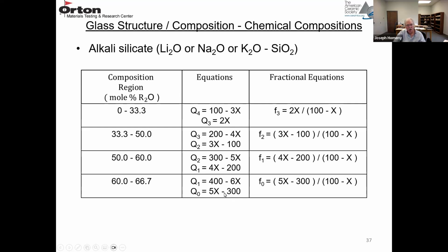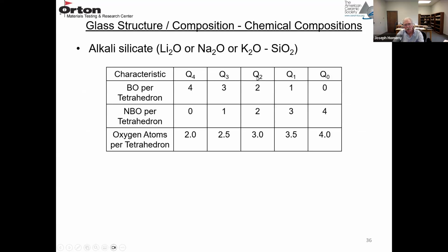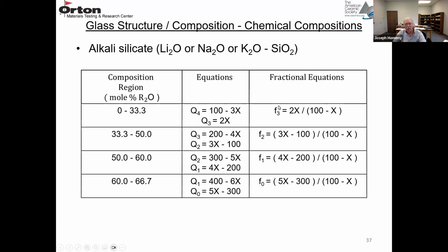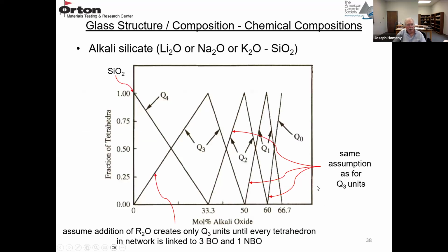So you just put in the values for X, you can calculate the amount of Q4, Q3, Q2, Q1, and Q0 units. And then this is the fraction of a Q3 unit, a Q2 unit, a Q1 unit, and a Q0 unit. So if you do those calculations and make the plot of fractions of tetrahedra versus mole percent alkali, it looks something like this. So here's Q4.